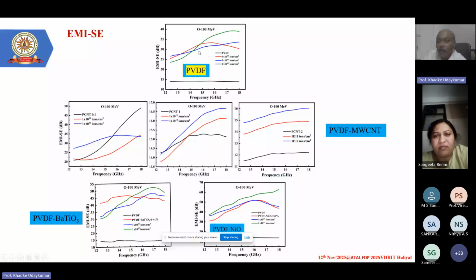Energy remains the same. But when you go beyond 10 to the power 12, reaching 10 to the power 13, the maximum amount of damage will take place. Free radicals will be generated, and our theory predicts that in the absorption, multiple reflection is taking place, which leads to a huge amount of EMI SE, almost of the order of 40 decibel at the frequency of 16 to 18 gigahertz. In the same way, for carbon, one problem we observed is that when we have PVDF with carbon nanotube bombarded with oxygen, we get reduced EMI SE. As predicted, when carbon nanotubes are bombarded with oxygen, they suddenly become amorphous. And when they become amorphous, they lose their complete characteristics. That is the reason EMI SE is drastically reduced. So that is what has been shown here.